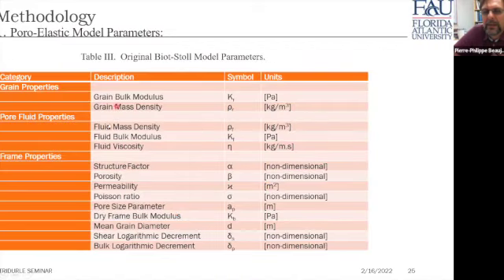Now, again, we use 14 physical parameters in the Biot-Stoll model, or the poro-elastic model we use. And we match all these parameters using a comparison between the model and the measurement we make. We match the modeled acoustic signature and the measured acoustic signature to identify the value of these parameters. And the values of several of these parameters will change as cracking takes place.